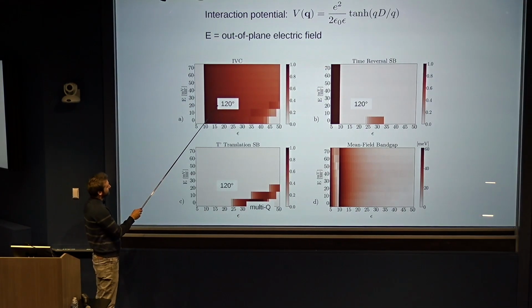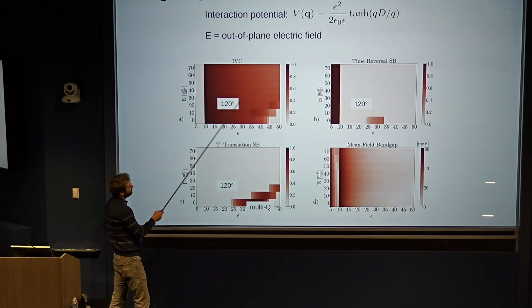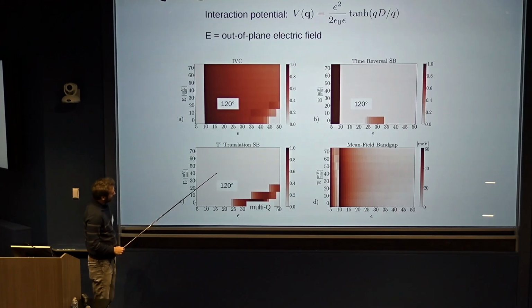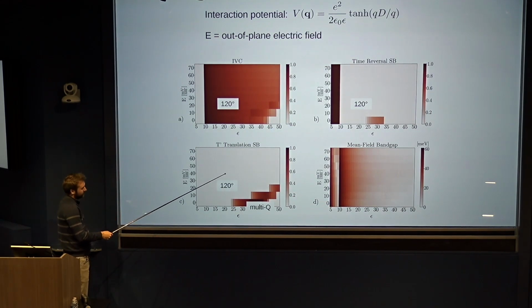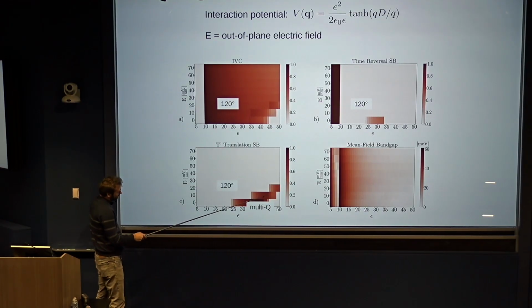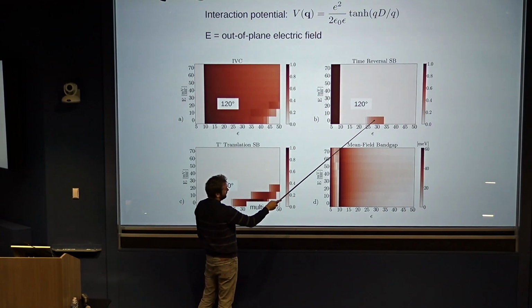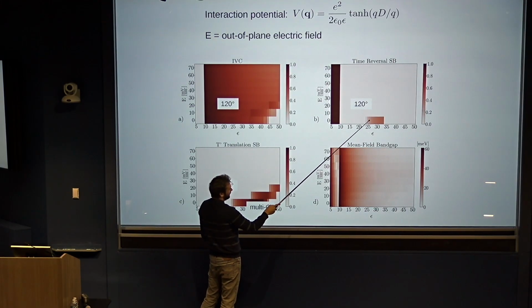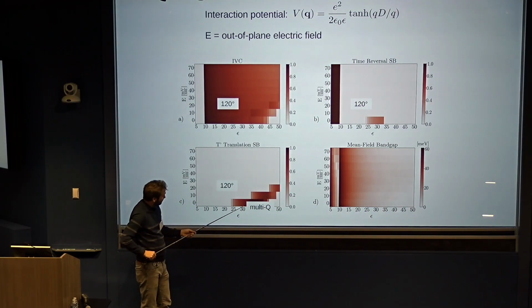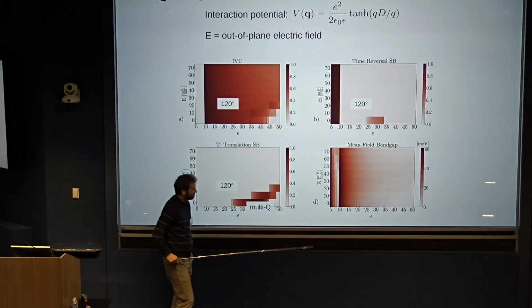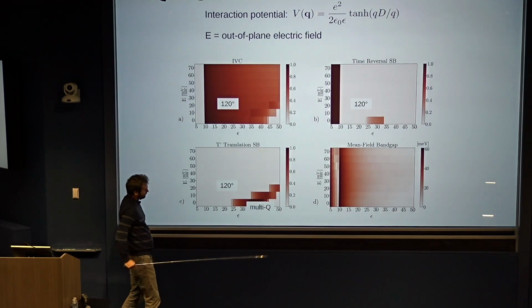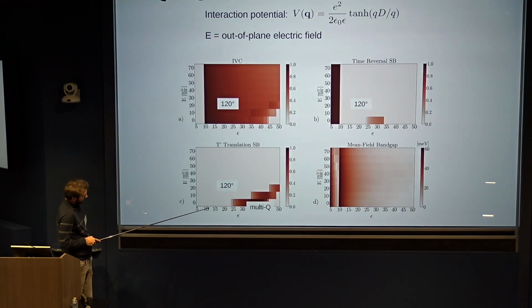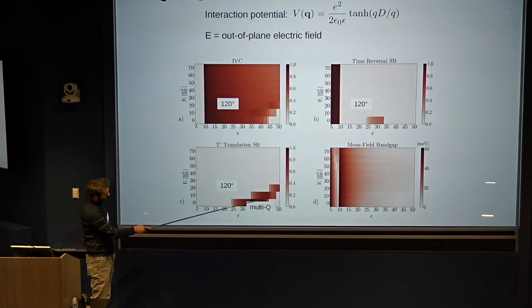Here is, like I said, the 120-degree state. It has in-plane magnetism, no out-of-plane magnetism, and it's invariant under translating and rotating spins along the z-axis by 120 degrees. But then we see this other region appear where this modified translation symmetry is broken, and in a part of the phase diagram it also breaks time reversal symmetry, so we also get a translation symmetry breaking state which has an out-of-plane magnetic moment. These are the multi-Q orders that I was talking about. We find them at moderate values of the dielectric constant, and at around 0 displacement field.